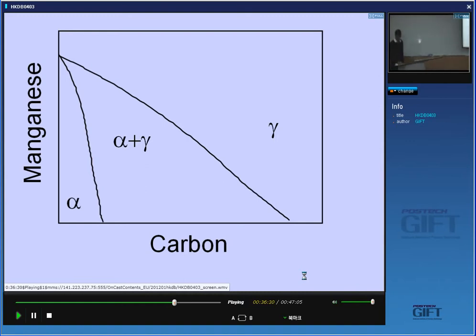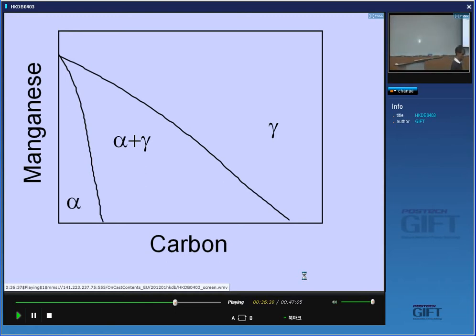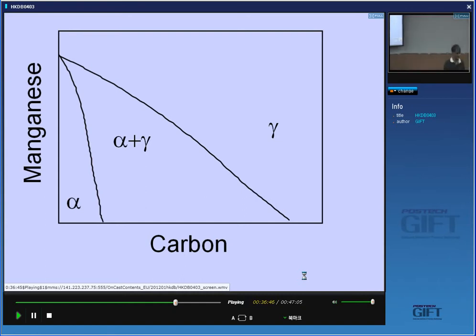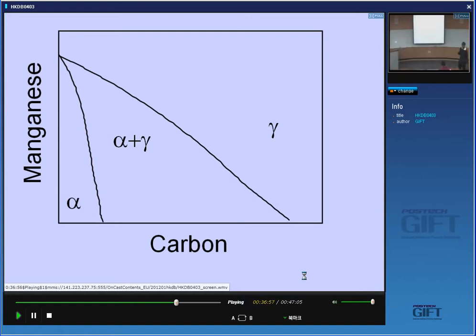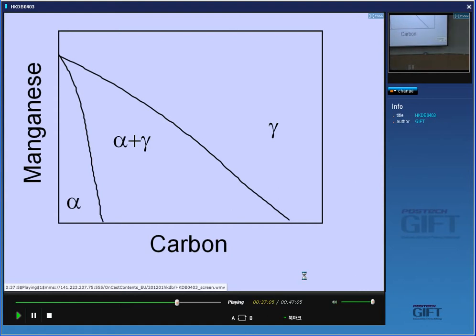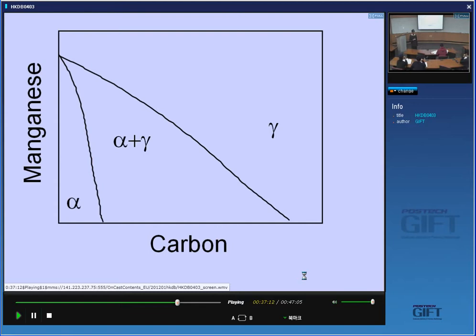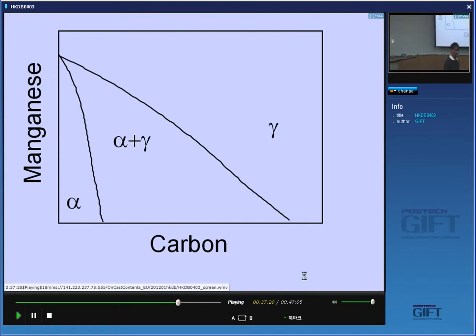If you use programs like DICTRA, you will find that as you lower the transformation temperature, the diffusion spike — the concentration gradient of manganese — becomes extremely narrow and steep, until it gets to atomic dimensions. And that's not physically correct; we cannot tolerate concentration gradients which are that large because other effects come into play. You get to a point where manganese simply will not move — carbon is able to move, but manganese is not. So as you lower the transformation temperature, we will get to a point where you can no longer have equilibrium; the manganese is effectively frozen and is trapped as the ferrite grows.